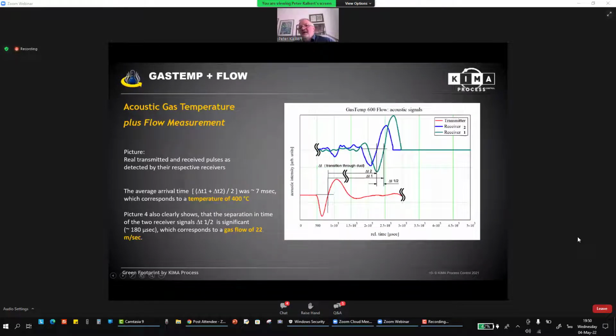And here you see what is happening. Once again, here we have a real signal that was transmitted. You see the blue signal is the one which was going with the flow, and it arrived earlier than the other signal, which was traveling against the flow. And we have a time difference here in the range of 180 microseconds. This corresponds roughly to a gas flow speed of 22 meters per second. And the average was around 7 milliseconds through a duct of 3.5 meters, and this corresponds roughly to a temperature of 400 degrees centigrade.